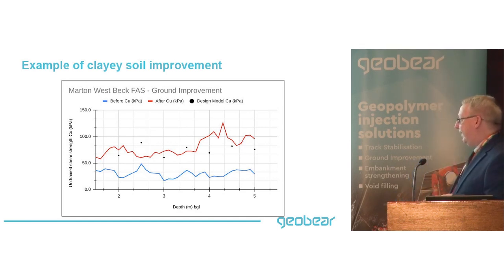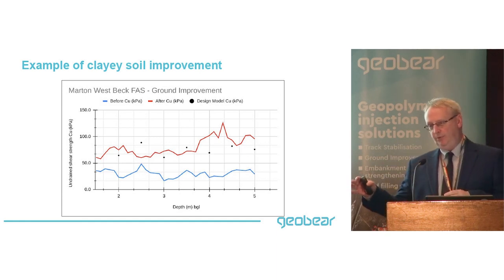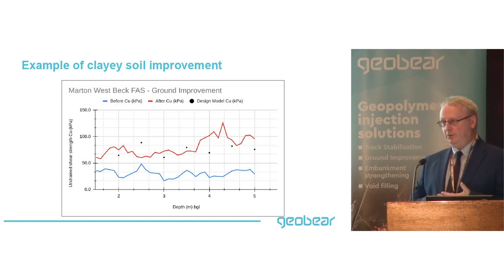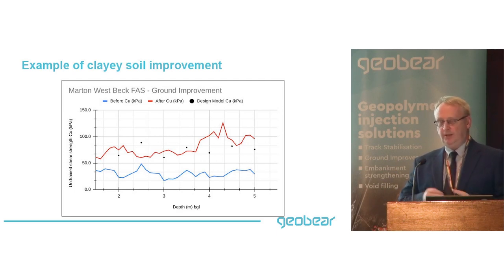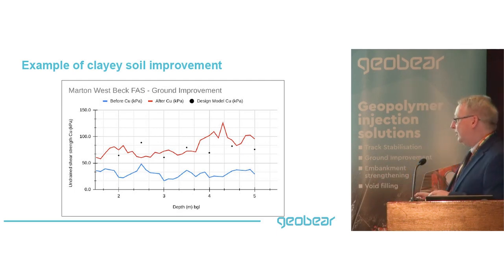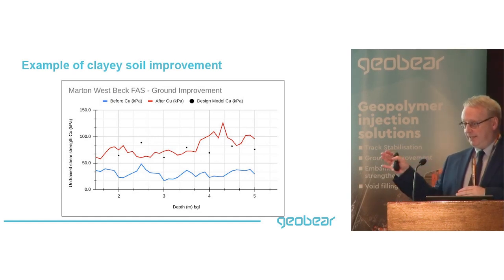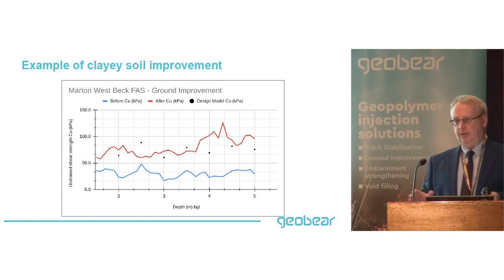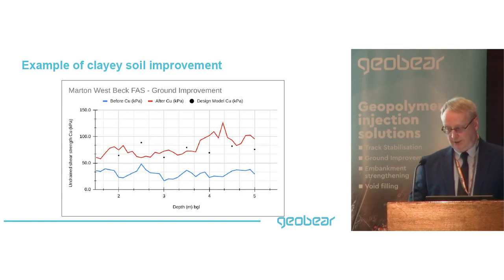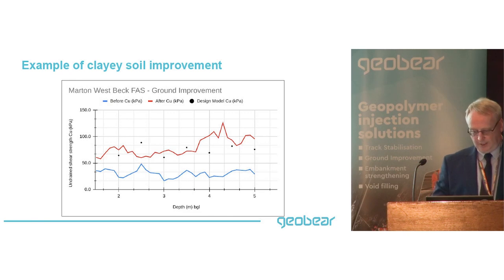The red line is after treatment, and we did a model that predicted what the performance would be, shown by the black dots. Our actual performance closely matches our model - this is how we model what we think is going to happen, including how many kilos, what depth, what spacing, which polymer. That's our design, and it's been proved in the field on many occasions that we're pretty good at calculating exactly what we need to do. This is not a guesstimate, it's an actual calculation - quite different to how this has been done in the past.